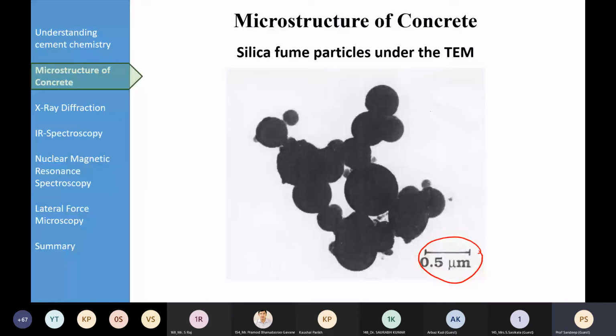And those who have been working in concrete technology know that in the recent version of Indian Standard 10262, they have defined a separate mix design procedure for high strength concrete. While defining the mix design procedure for high strength concrete, they have suggested the use of silica fume. The reason for the use of silica fume is this only, because it has quite smooth and spherical particles and small size. So it gives a very large surface area for the hydration reaction, which means a large amount of hydrated cement paste or CSH gel, which in turn means good strength.